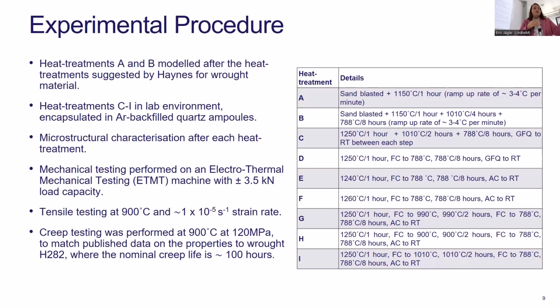The rest of the heat treatments were lab-based ones, so we encapsulated all the samples in quartz tubes, and we heat treated them in lab furnaces under a range of different conditions. So you'll notice that we have a much higher solution heat treatment, and we played around a little bit with the solution heat treatment, and I'll come to that in a second why. The other thing that we did was look at the intermediate aging step. So the current Haynes 282 recommended for cast and wrought is super solvus, super gamma prime solvus, whereas we looked at a couple of heat treatments sub-solvus to see what that would do to the material and its properties. And then we kept the gamma prime optimization to 788, just because that seems to work quite well anyway.